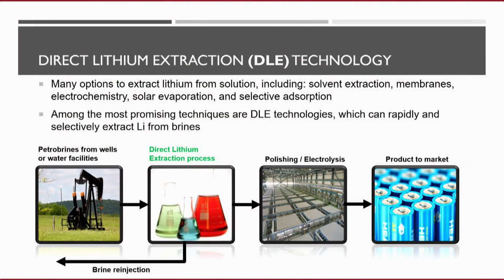One of the primary technologies is called direct lithium extraction. And so what you would do, and this is what I'm going to talk about in the few remaining minutes, you get these brines, so they might be petroleum brines, or you might actually drill wells to target areas that have high lithium concentrations. It goes into this direct lithium extraction process, and what that does is selectively strip out that dusting of lithium from the brine and also concentrate it in an acid, which I'll show you in a bit. So you start with a vast volume of brine, you end up with an acidic solution that's much smaller, has a much higher concentration of lithium, and most of the impurities have been removed. And that fluid, which we call the concentrate, can go for further polishing or electrolysis to make the battery salts that go to market.